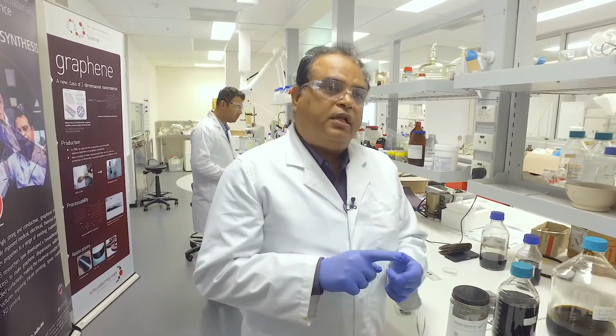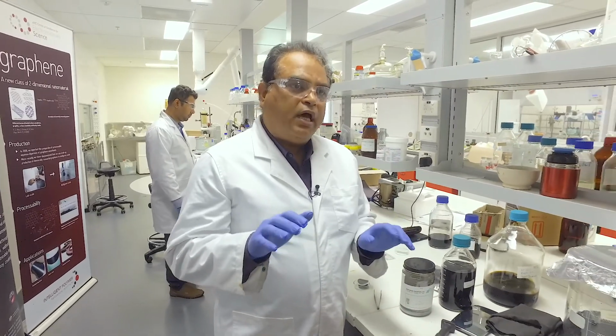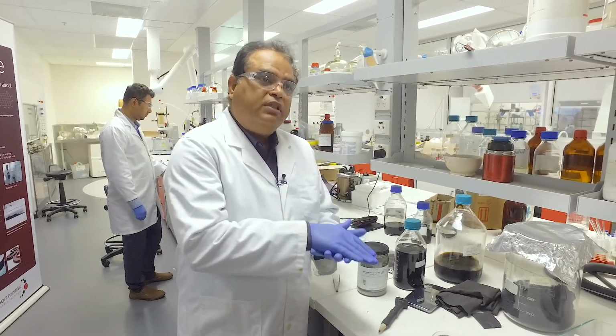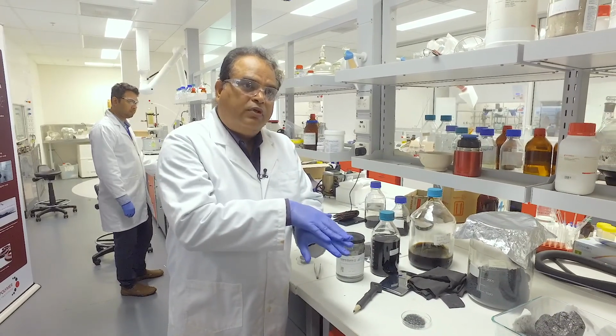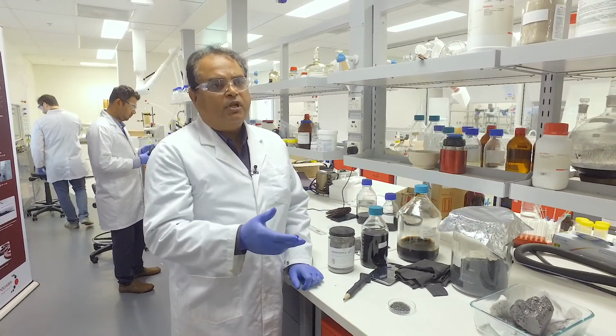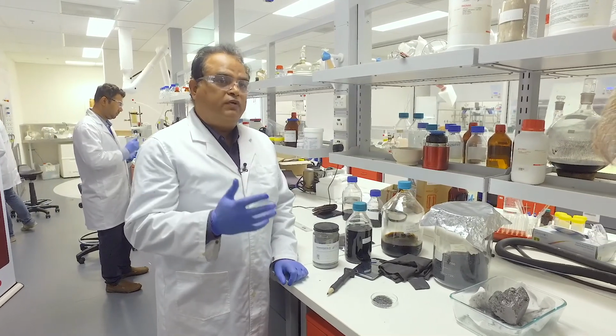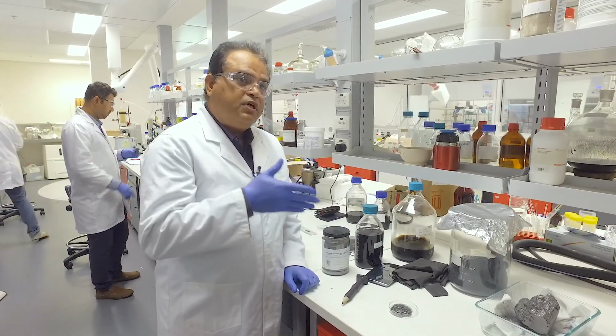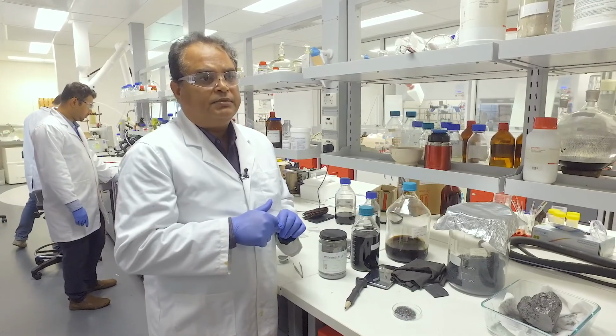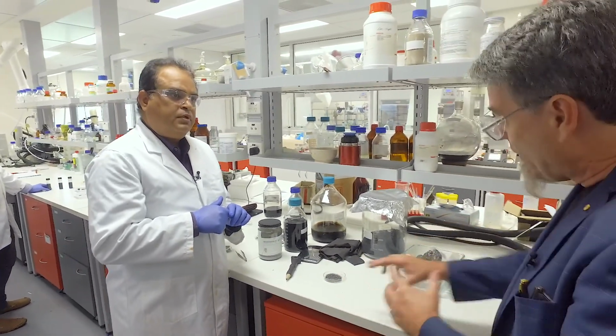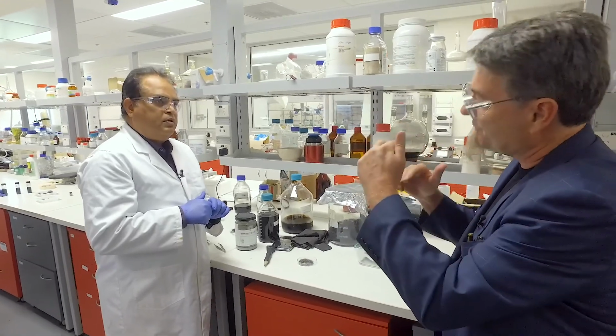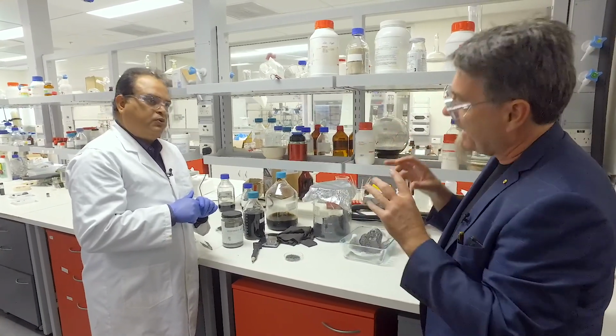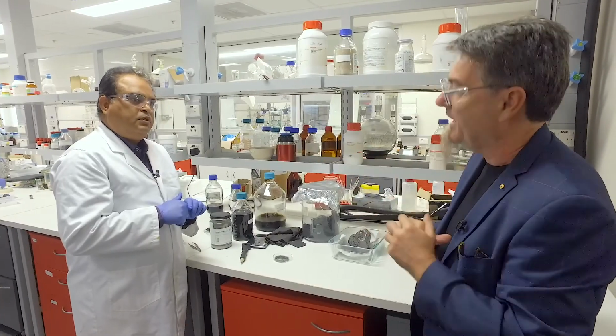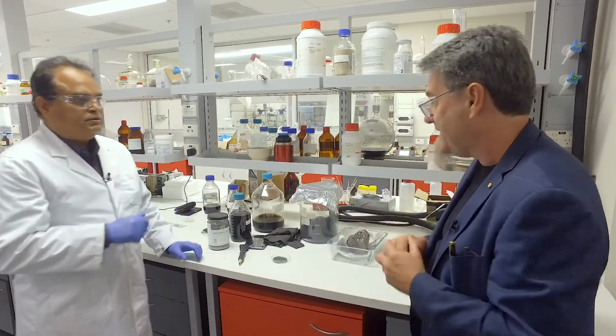And that intercalation involves putting other ions between the sheets of graphene in these flakes. These intercalants need to be of very high boiling nature because they need to stay within the space of the graphite. So we have been optimized, like orthophosphoric acid, nitric acid, and sulfuric acids are the main intercalants which we have been using for intercalating the graphite. So we take this lump of graphite, we grind it into flakes, and then those flakes have multiple sheets of graphene, and you're putting ions in between those sheets of graphene. Right. Yeah, that's right. And then the next step would be?